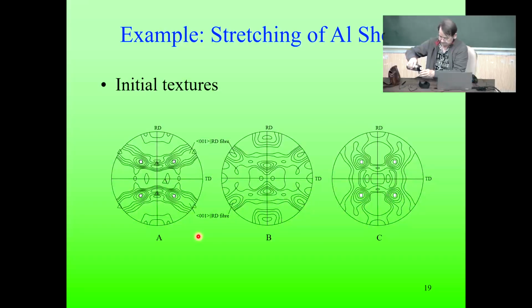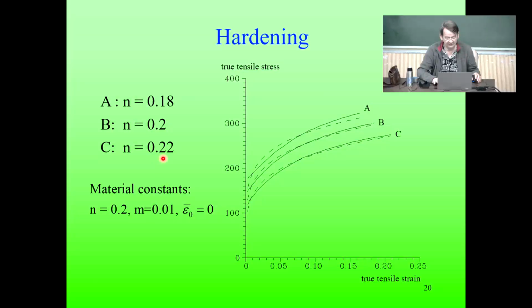Here I show the textures. See, it's a kind of fiber and kind of quite strong cube component is there. Here the cube component is weak in this texture, and here it's again like a 90-degree rotated version of this one. Okay, and the hardening was simulated, as I said at that time, using this Holloman type of equation. The simulation is not that perfect. Since then we are doing much better, but this was the fitting at that time.